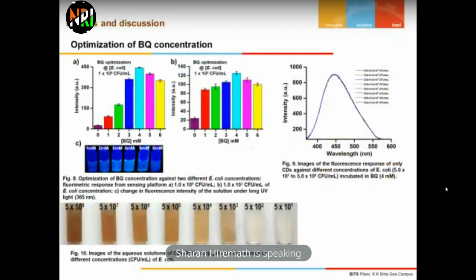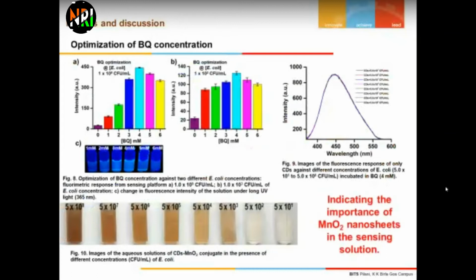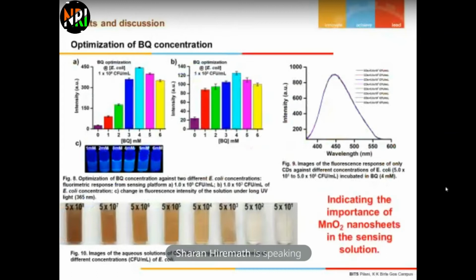And below we can see that even the sensing system can be used for visual detection of E. coli. As the concentration of E. coli is very low, the color of the solution is almost colorless. As the concentration increases, the color has turned brownish. So this shows that MnO2 plays a major role, apart from CDs and benzoquinone, in the sensing of E. coli.